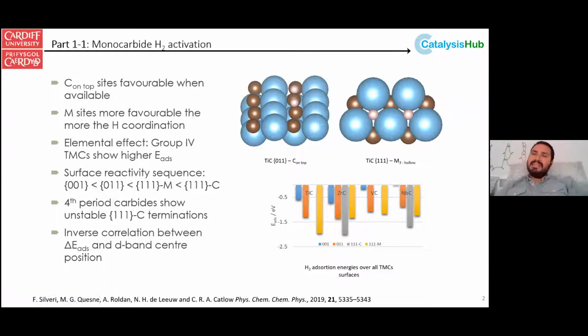For a lot of experimentalists, these can be formed via coking and are considered quite a pain because they're very stable ceramics, but they have interesting catalytic properties that are actually quite similar to the precious metals, particularly palladium or platinum. They can catalyze the reverse water gas shift reaction and some of the CO2 hydrogenation reactions. There are quite a few interesting reactions that these materials catalyze, and particularly the middle group transition metal carbides have very interesting reactivity. Our targets were titanium, zirconium, vanadium, and niobium carbides, so all the early transition metal monocarbides.